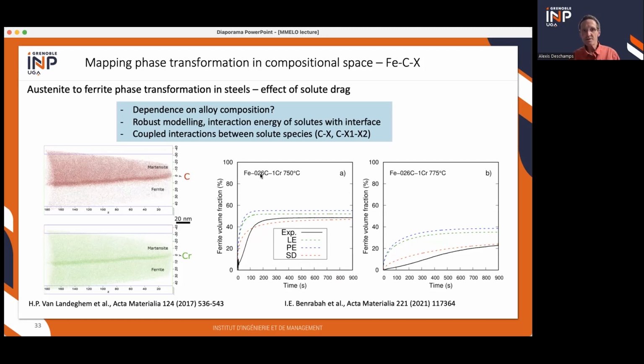And so the question was, how much does this solute drag depend on alloy composition? And can we get a robust modeling of this solute drag, which would be able to describe a whole set of different compositions? And then you have coupled interactions between solute species. So this could be a coupled interaction between carbon and chromium, and maybe between carbon and different solute species if you are in quaternary or more alloys.